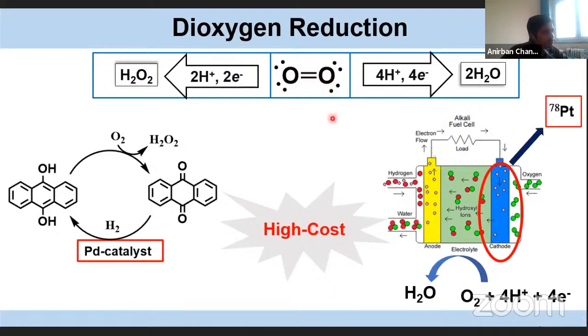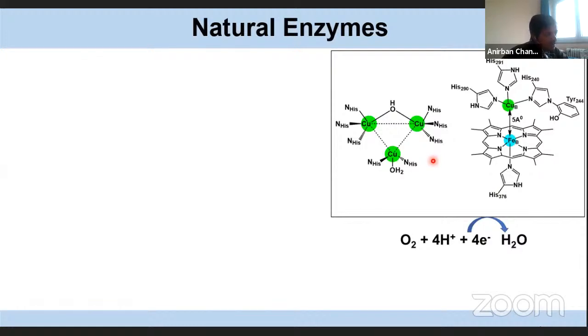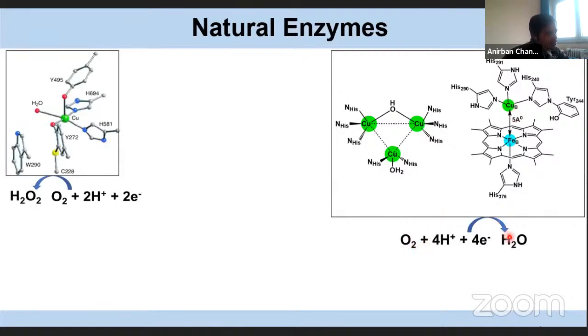So we can see that for the fuel cell and for the generation of hydrogen peroxide right now, 4d and 5d metals are used, which always increases the cost, and also we have to compromise with the efficiency of these cells. However, if we look into nature, we can see that several enzymes use cheap transition metals in their active sites, and they selectively reduce oxygen to water or to hydrogen peroxide. Here I show some examples: cytochrome c oxidase, where an iron and copper binuclear metal center is involved in its active site, and a trinuclear copper center is involved in laccase, which selectively reduces oxygen to water without producing any partially reduced product, which is very important. And other copper based enzymes such as copper amine oxidase and galactose oxidase are responsible for selective two electron reduction of oxygen to hydrogen peroxide during the substrate oxidation process.